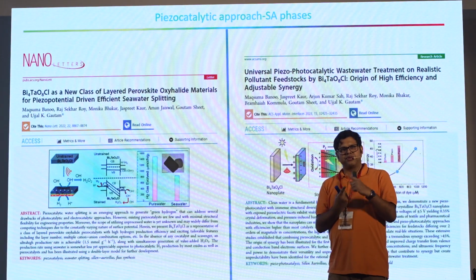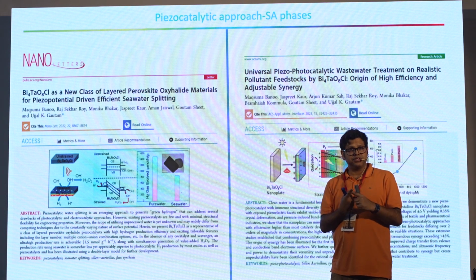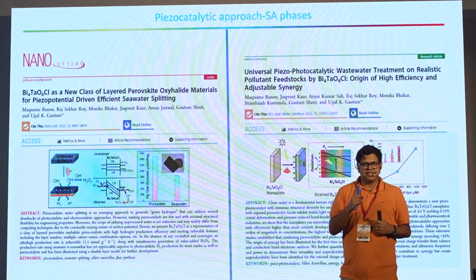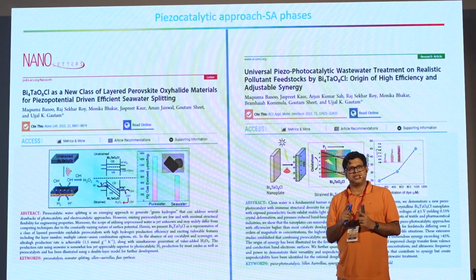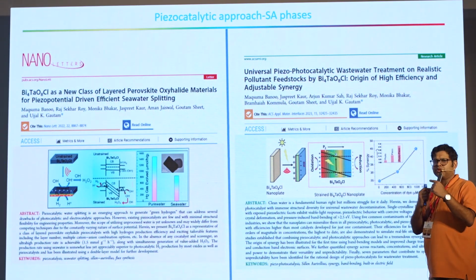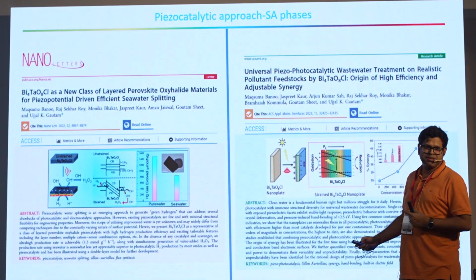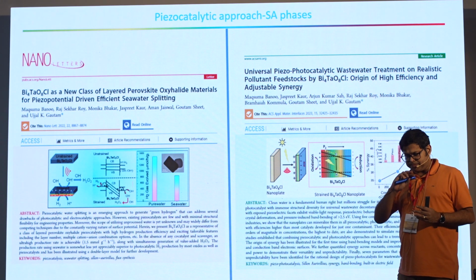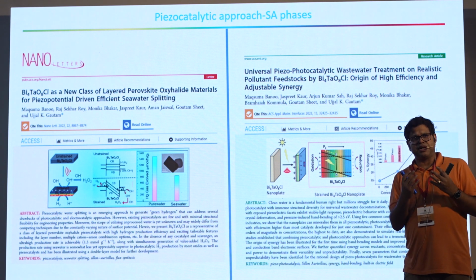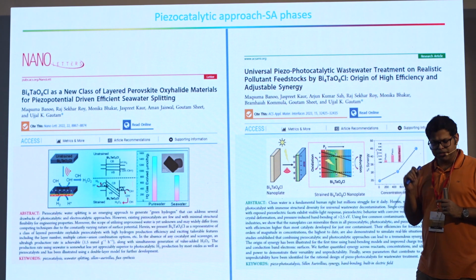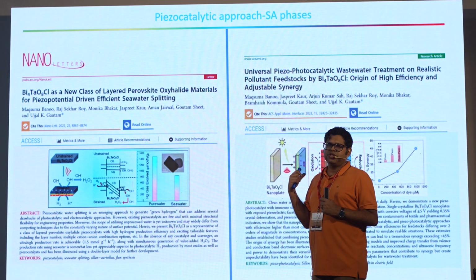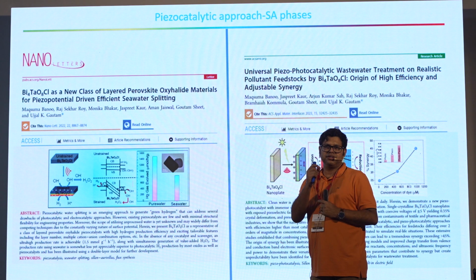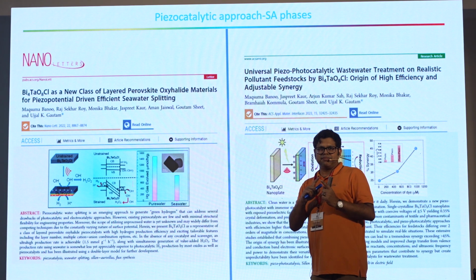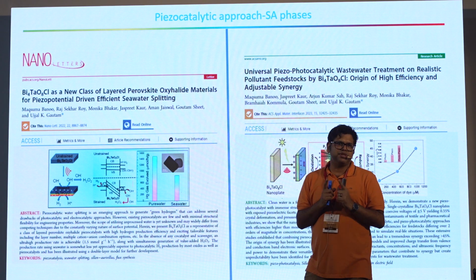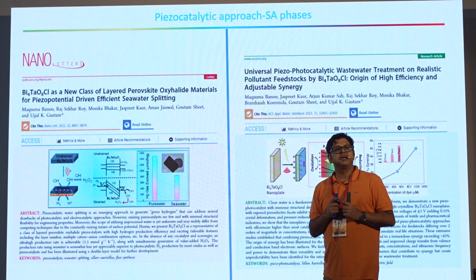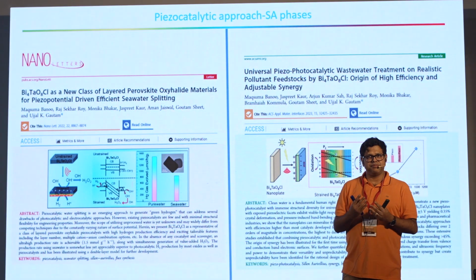So it is a valence band phenomenon. Now when we combine photochemistry and piezochemistry, we combine both excited state phenomena as well as valence state phenomena. So when you combine both of them, we end up getting something called synergy. This is a very interesting paper. We have figured out the origin of synergy, where it comes from. There are about 7 independent factors which contribute to this synergy. Once we understood what happens, we have used it for pollutant degradation. The main difference compared to the conventional work is that we use pollutant feedstock at industrial concentrations, very high concentrations.